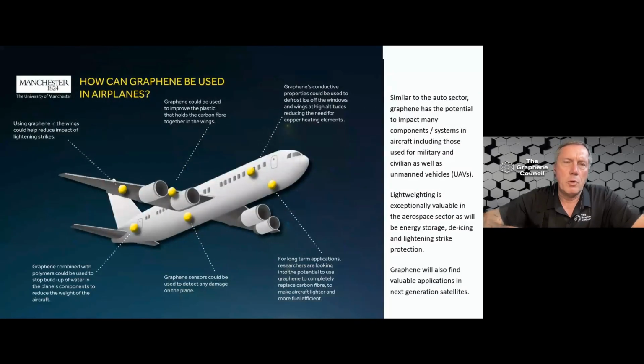And as I mentioned, the same would hold true for aerospace, and in particular, lightweighting is really one of the key objectives there, as it is in automotive. And that's where graphene, by making composites stronger, you're able to use less material, or in the case of using fiber reinforced systems, whether it be glass, basalt, or carbon, we have examples where if let's say you had a 5-ply reinforcement for a composite part, and by strengthening the resin system with that fiber reinforced system, you're able to eliminate 1 or even 2 of those 5 plies.